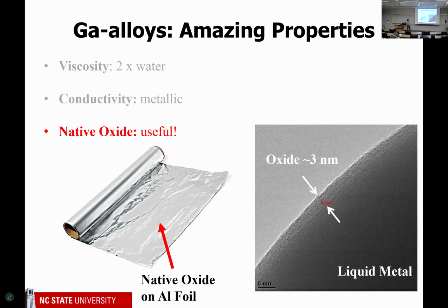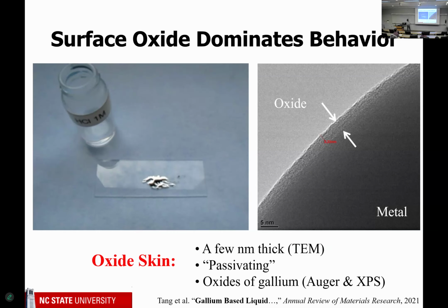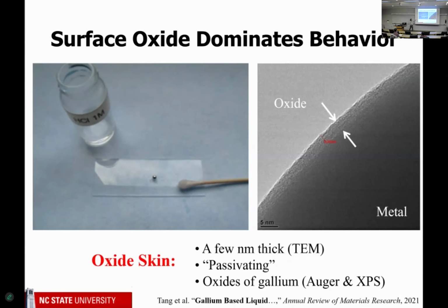So, well, why is this useful? If you want a metal, you don't really want an oxide. But this is particularly useful in this case, so please watch, because this is the liquid metal on a glass slide, and if we use a little bit of acid, it will dissolve away that oxide layer, and without the oxide skin, the metal just beads up due to surface tension. Oh, by the way, gallium has the largest surface tension of any liquid at room temperature known to man. So another interesting thing about it. And so that's why it's beading up. But with the oxide, obviously we can spread it out like wet paint.